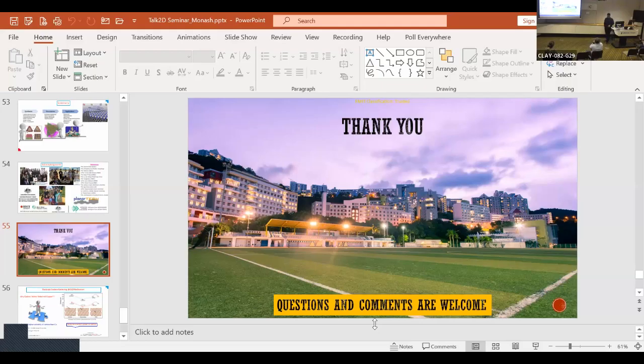Yeah, that is a very important question. That's what I also put there as one of the drawbacks of CVD. That's the reality. CVD at the moment is known as one potential candidate for scalable growth. But the main issue is the high temperature, and CVD normally takes a longer time, so it's not an energy efficient process. That's why we're trying to create processes which use lower temperature, like laser CVD, which is quick, just flash it and get the film. These kinds of processes we have to develop if we want to move into industry and make it compatible.